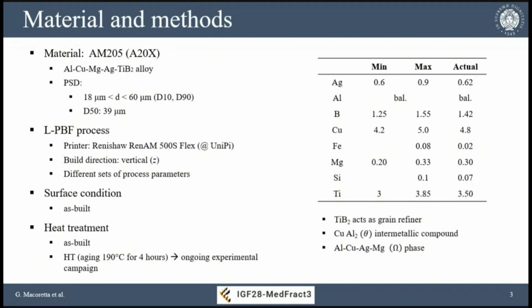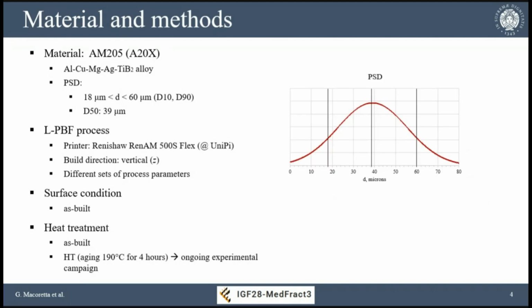The powder we are using is a standard powder for L-PBF, having a PSD with a central value around 39 microns, with the extremes, the D10 and D90, between 18 and 60 microns. It's a good powder distribution for printing with a layer thickness of 40 microns, which is what we adopted in this phase of the process.